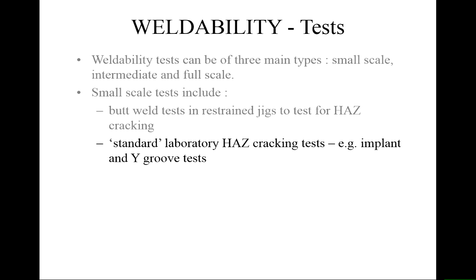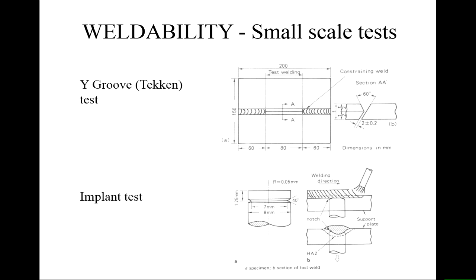You can get some standard laboratory tests like implant tests, some Y-groove tests. I'll show you a picture of these in a second. But they're all done in the lab. And the idea is to get a procedure which you think you're going to work with. So the Y-groove test, you can see here, you've cut a V-shaped groove in half, and then the grooves are in the same direction in here, so it looks like a Y shape. You put some constraining welds on either side to be full, and then you weld in this patch here, and you look for cracking in the bottom here. Implant test, you have this implant, you stick it in, you weld across, and then you've got something you can pull out to measure the mechanical properties of the weld test. So these are standard tests. You can look up the procedures. They're in the standards and things like that. They can only tell you that the welding procedure made a good weld or a bad weld in the lab. They don't tell you what's happening outside.